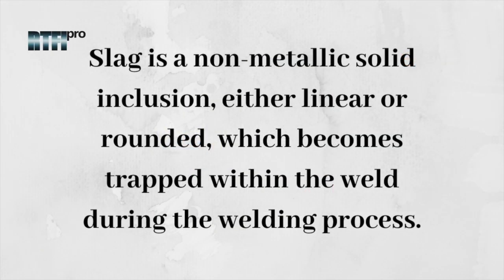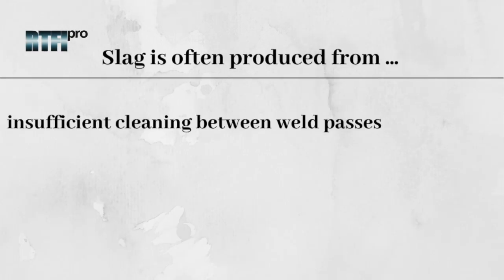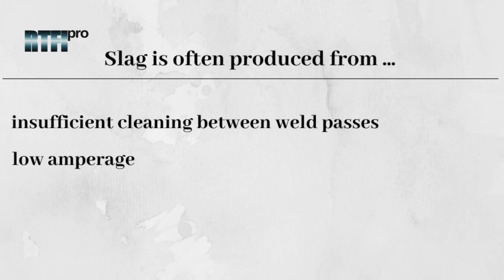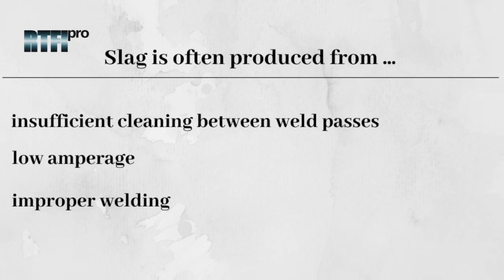Slag is a non-metallic solid inclusion, either linear or rounded, which becomes trapped within the weld during the welding process. Slag is produced from insufficient cleaning between weld passes, low amperage, improper welding, or when attempting to weld in an area that is too tight.